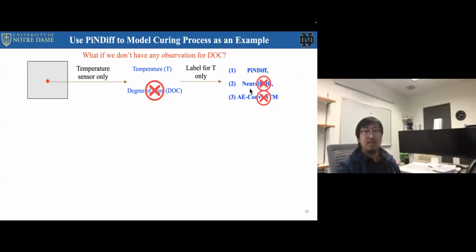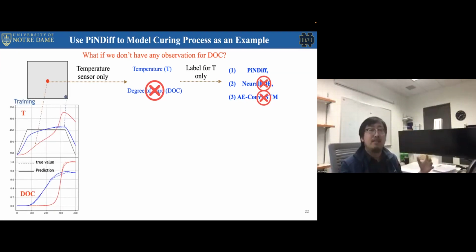You have zero data. So in this case, the two baselines won't work. But like I mentioned, the heat transfer and the dynamics, the degree of cure kinetics, are coupled, in the sense that we integrate those PDE operators into our network. So in general, we can leverage the relation and make the connection. So we can train the models with the temperature data only, and then we can basically predict the degree of cure as well. It's more like an inference of the hidden physics.